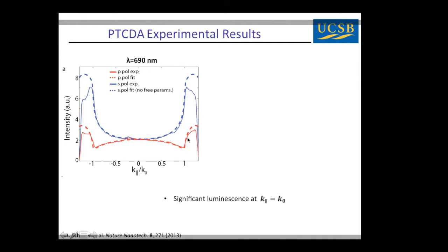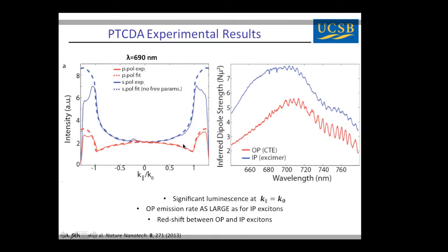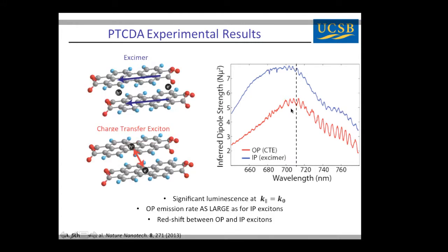Okay? So when we do our fits, the dashed lines again are fits, what we see are two different spectra. These are the results of fits again, and we can back out the extrinsic collection-dependent effects from our optics to get at something like an intrinsic dipole strength. And we can see that our out-of-plane oriented dipoles, if you kind of draw a line, are sort of shifted in space. Okay? So the idea of what we think we're seeing here is that in the system we have two types of excitons, a normal intralayer excimer state with an in-plane dipole moment and a charge transfer state where we actually separate the electron and hole between two molecules.